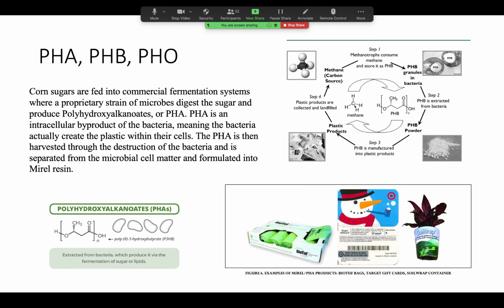And there are some marine standards where this says it is actually marine degradable, and that's really important because you hear about all this plastic that comes to the ocean, and the problem is that this biodegradable, compostable material, as we talked about, needs to be in very special conditions, and the marine environment doesn't have the special conditions that these more commonly degradable materials need. So that is one of the downsides. People think it's going to be the end of the pollution, but it's really not, because if you don't have the right conditions for it, or the right enzymes, or right concentration of microbes, or just the right microbes at all, it's not going to get there.